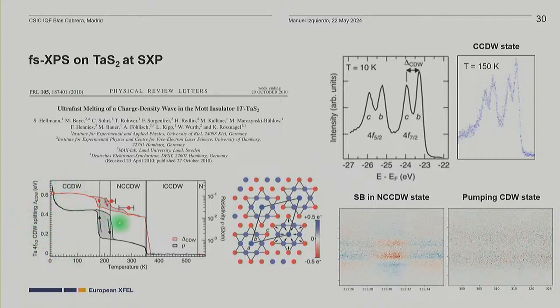It's very interesting that you can follow this evolution by measuring the tantalum 4f core levels, because the charge density wave is going to induce splitting that depends on the temperature, and you can also analyze it as a function of pump-probe. So this is what was measured in 2010 at FLASH. You see here the two peaks that appear when you are at low temperature in the charge density wave phase.